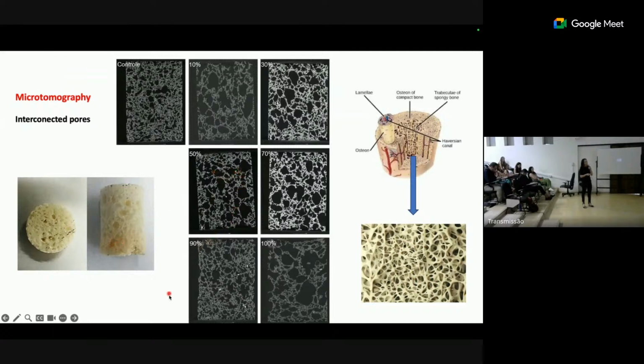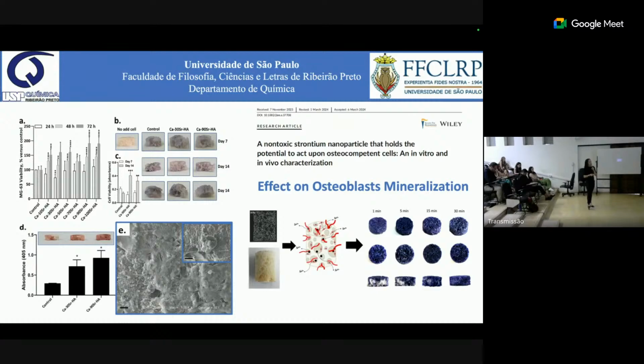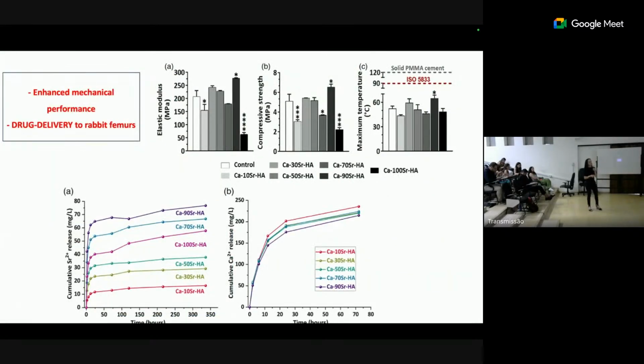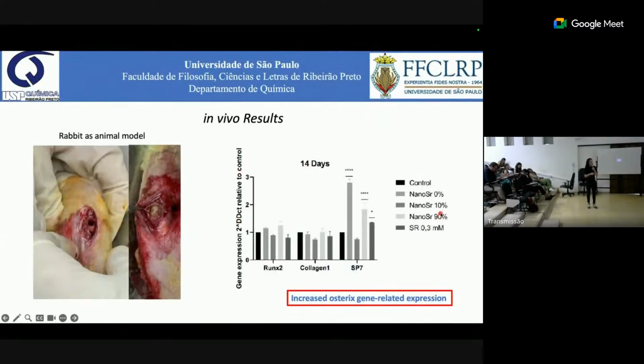The micro-CT analysis showed that we have a porous and interconnected structure that can also favor vascularization and cell penetration. The materials were able to stimulate mineralization by osteoblasts. The cells were able to penetrate the structure of the cements. The materials were able to release strontium and calcium. So all the positive effects we found in the regulation of osteoblasts and osteoclasts were related to the release of these ions by the materials. And after implantation, the presence of implants induced a higher expression of the Osterix-related gene, which is a late marker of cell differentiation.